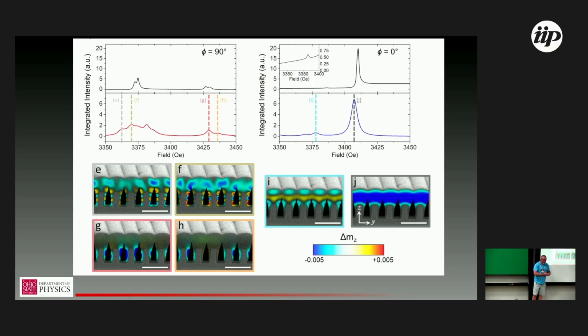And so something that I glossed over, this is another one of my students, Michael Chilcote, who did this work, is, this was not an on-purpose patterning. It's a very strange shape. But what he was able to do was take this SEM image and extract exactly the shape of the real magnetic material that we have and use that for the numerical modeling. And basically it perfectly predicts what we observe. And what you can see happening is that this throwaway material in the trench, that's this very thin U-shaped layer, in fact supports substantial magnon resonances. And so the two peaks here that come together and then anti-cross are essentially trench modes and nanowire modes that are sort of independently excited and have different symmetry with respect to angle.